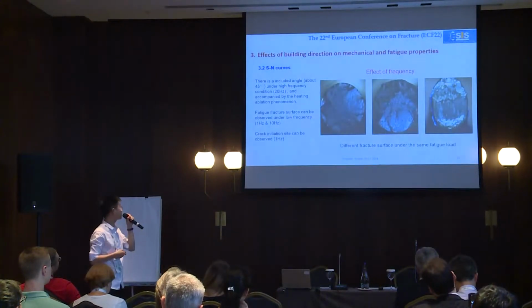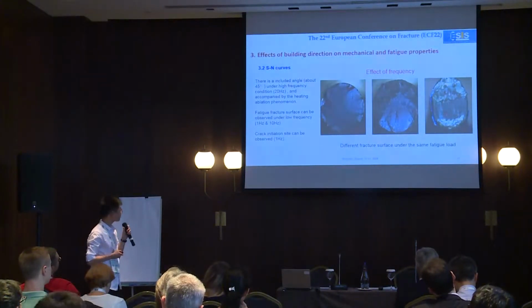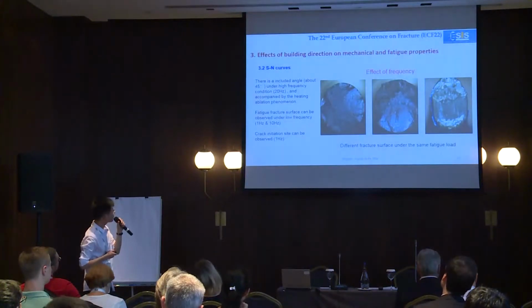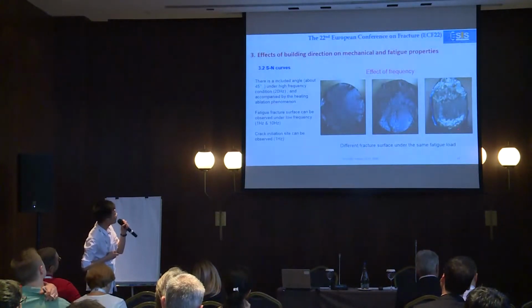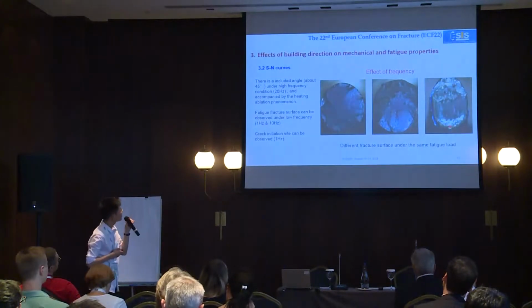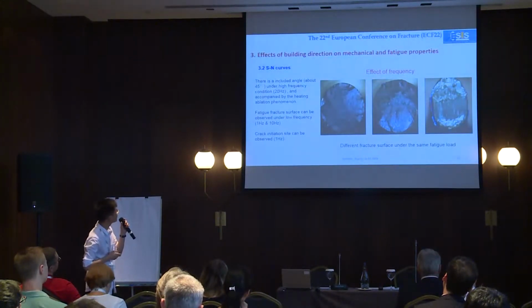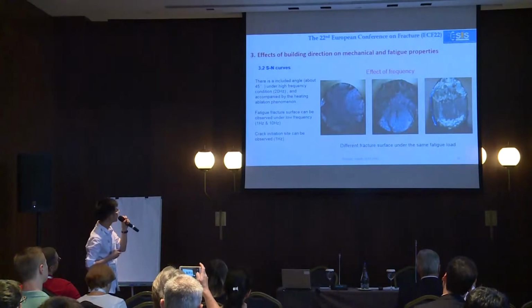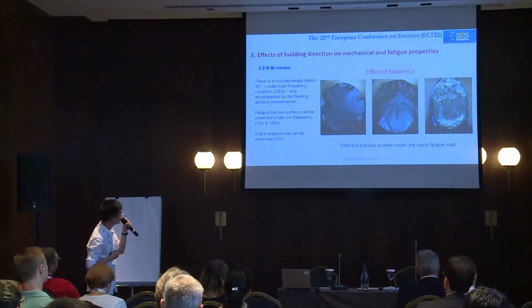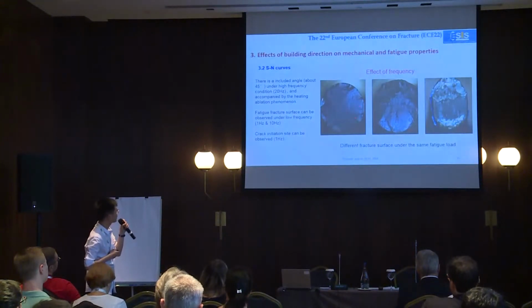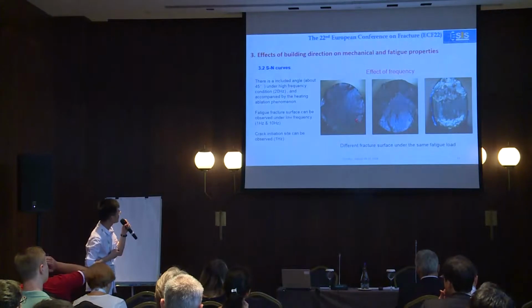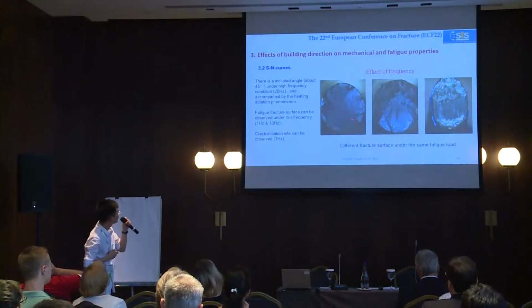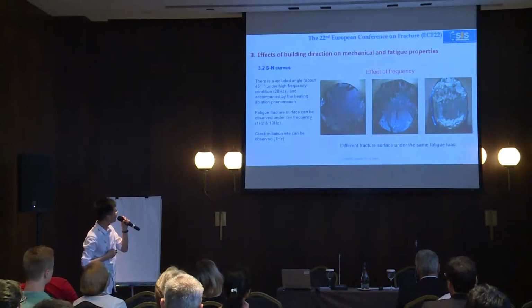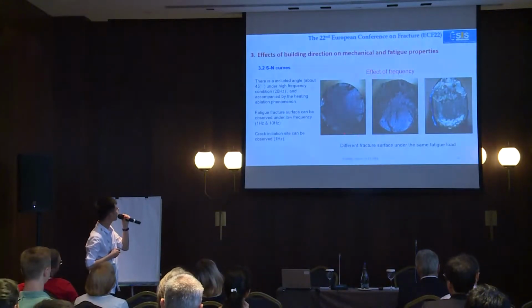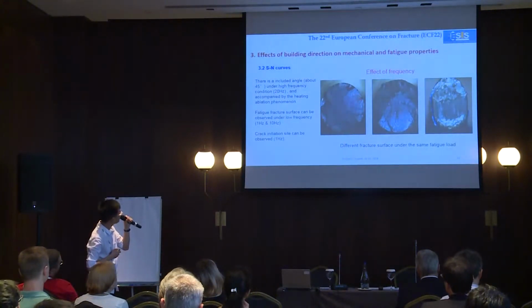This picture shows the effect of frequency. When frequency equals 20, it's just like this. When in low frequency, the fatigue fracture surface is vertical to the load direction, and we can find this arrow and this arrow. But when frequency equals 1, there are some dots in there.